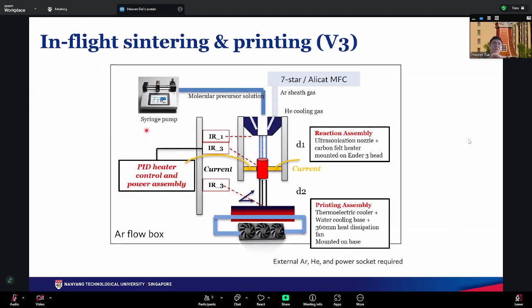Additionally, there is the in-flight sintering. I'm not sure if I showed this in this group. Previously we had the hydrophobicity issue. The reason is that we use carbon thermal shock, which heats up the substrate. But now we don't heat the substrate at all. We have a syringe pump pushing the precursor solutions through an ultrasonication nozzle, and we spray the micro-sized droplet particles directly as a stream through a 1000, 2000, 3000 Celsius degree carbon thermal shock mini furnace, and then it's ready to coat on top.